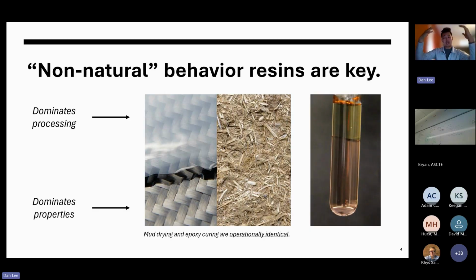The top is a completely cured material, 100% cure, and the bottom remains 0% cure. And it happens heterogeneously. In a traditional cure, you have your whole volume of resin curing together. If you measure the rate of cure at any point during a traditional cure, it's the same everywhere. In this case, you have a very fast cure in some regions and 0% rate of cure in other regions. This opens up all sorts of new ways to think about continuous processing of batch-wise processes, and we can talk about all sorts of other things it enables.